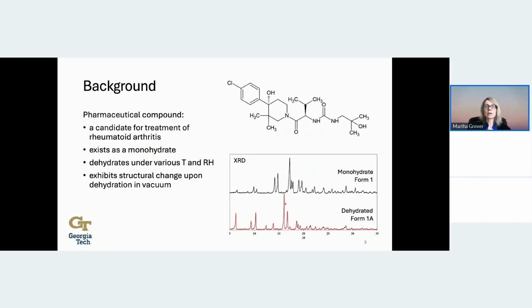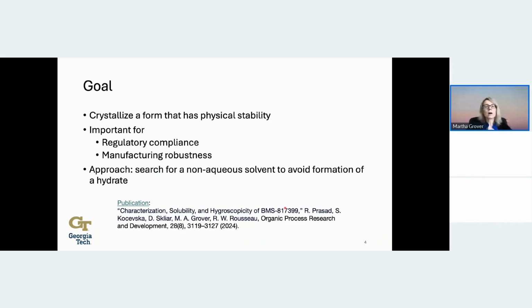And so this structural transformation was observed to occur, and that was viewed as undesirable, in that we wanted to have a crystalline form that had physical stability. So this would be important for regulatory compliance, to have a documented form and then to maintain that form, to maintain, for example, bioavailability. Also for manufacturing robustness, we wanted to have a form that could be robustly manufactured. And so the approach that we initially took in this study was to search for a non-aqueous solvent and thus avoid the formation of a hydrate.